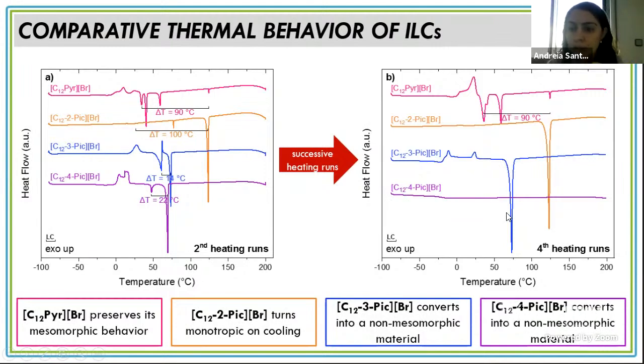In order to understand what happened to the LC behavior after successive heating runs, the right figure includes the 4 heating runs for each material, and it's possible to observe that C12 pyridinium bromide preserves its mesomorphic behavior, as it is possible to detect the same 3 transitions even though 2 of them are not completely deconvoluted. However, for C12 2-picolinium bromide, the material turns monotropic on cooling, meaning that this transition is between a crystal and isotropic liquid. For C12 3-picolinium bromide and C12 4-picolinium bromide, both compounds convert into non-mesomorphic materials.